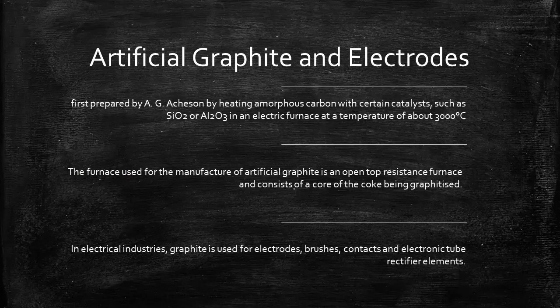The artificial graphite was first prepared by A.G. Acheson by heating amorphous carbon with certain catalysts, such as SiO2 or Al2O3, in an electric furnace at a temperature of about 3000 degrees Celsius. It is known that the industrial process converts amorphous carbon directly to artificial or synthetic graphite in an electric furnace. The furnace used for the manufacture of artificial graphite is an open-top resistance furnace and consists of a core of the coke being graphitized. In electrical industries, graphite is used for electrodes, brushes, contacts and electronic tube rectifier elements.